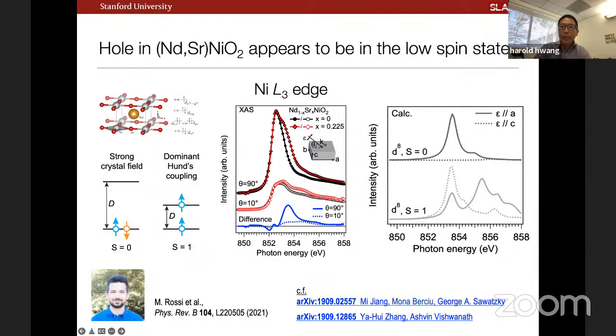Okay, another important early question that arose, and in fact, I think, let me see, in fall of 2019, I was visiting Harvard. I had given a talk on some of our initial results, and I had spoken with Yahui and Ashvin, and they and others were thinking about the nature of the spin state of these holes. And so we went to look at that in some detail, and the summary statement is that the holes appear to be in the low spin state. But the system is rather interesting because you're fairly close to the triplet state.